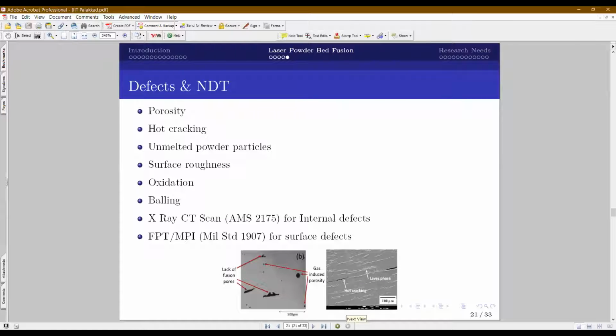and defects, which are the major challenge in 3D printing, and which we give more emphasis in the certification. There are about 6 defects I brought out here, which are very prevalent in 3D printing, like porosities, hot cracking, unmelted particles, surface roughness, oxidation, and some bald surfaces. And we typically use X-ray CT scan at this point of time for the internal defects, FPI for the non-magnetic materials, that is fluorescent penetrant inspection, and another one is magnetic particle inspection for the surface defects.